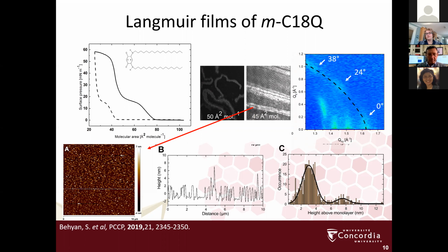They're quite broad, which suggests that we have varying degrees of either interdigitation or tilt or orientations or combinations thereof, in agreement with the multiple orientations of our head groups. The full width at half maximum of these peaks also corresponds nicely to the size of the head group.